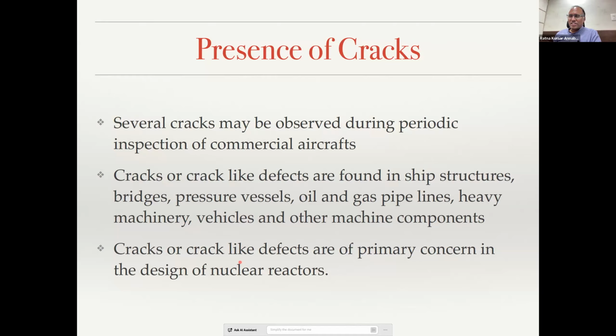Meaning, they will send ultrasonic waves and try to measure the length of a crack. All these structures will have cracks in them. No matter what you do, you cannot produce a product without cracks. There will be cracks, but are these cracks of such a size that one needs to be worried? That is what these periodic inspections will tell you. And if they are not critical, then they will let the flight fly. Otherwise, they will have to do some intervention.